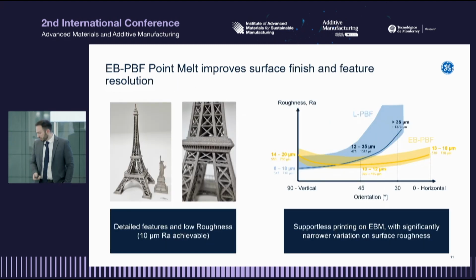Point melt can also do some cool things with supports and surface roughness. So those are the two that are back to back. And I have some toys to show, and you obviously won't be able to see them from there, but I will be around during lunch and can show you. A couple of examples of components that are much smoother than you would expect from electron beam components. And you'll notice the roughness plot on the right-hand side. The laser powder bed fusion, the blue curve, actually ends at 30 degrees of orientation from horizontal, and the electron beam one progresses. That's intentional.